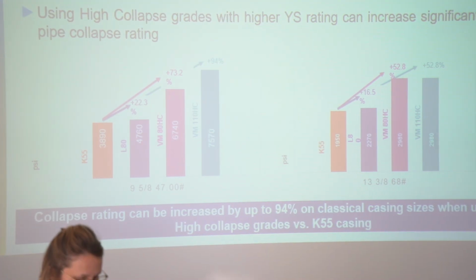I took here two examples, a 9 5/8 casing and a 13 3/8. You can see by using those type of high collapse grade, you can increase the collapse rating of the pipe. This solution has been on the market for oil and gas for decades, and we are now in the process to run testing at elevated temperature of all these pipes to replicate what really happened in situ in the wells. So that's to tackle the collapse issues.